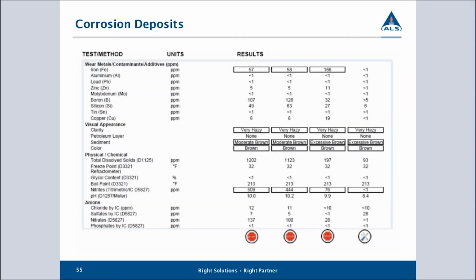All right, here we've got more serious corrosion going on. So we're seeing much higher levels of iron. We're noticing that the sample is now being described as very hazy, almost opaque. There's also a lot of brown deposits, and the coolant itself has turned brown from this. There generally isn't a brown coolant on the market, so this would suggest that this coolant is just carrying lots of rust around, which has discolored it.